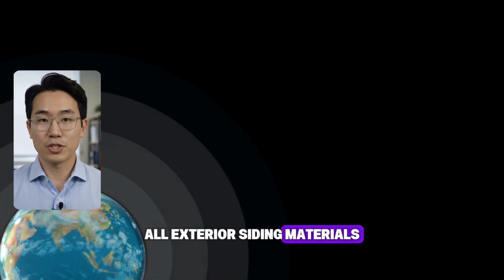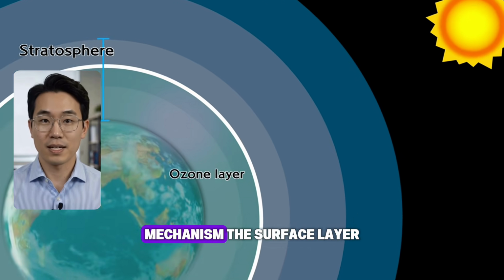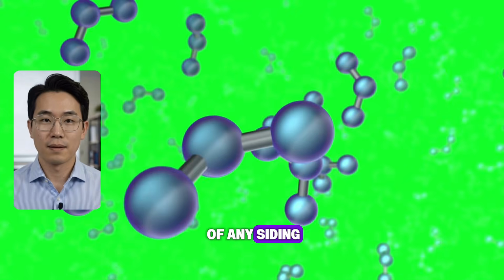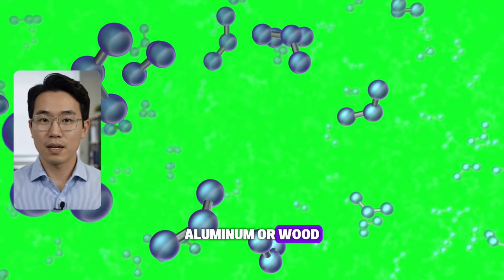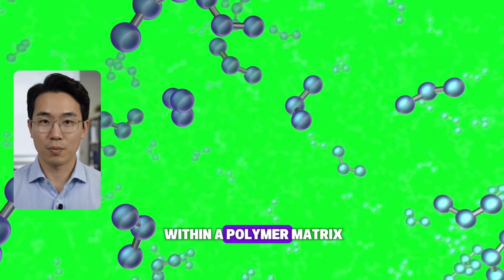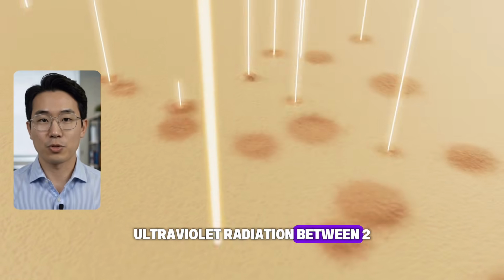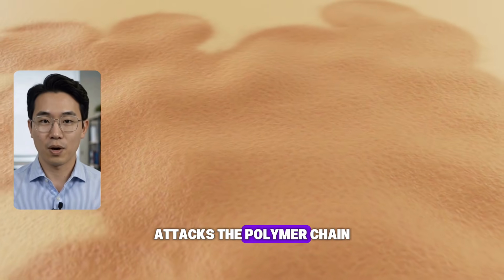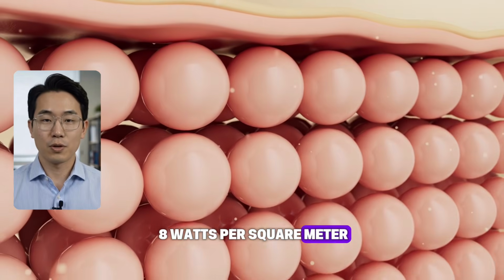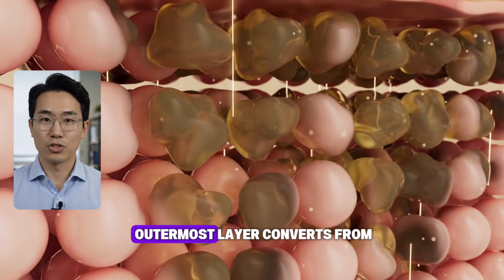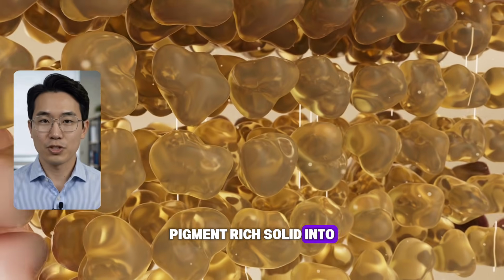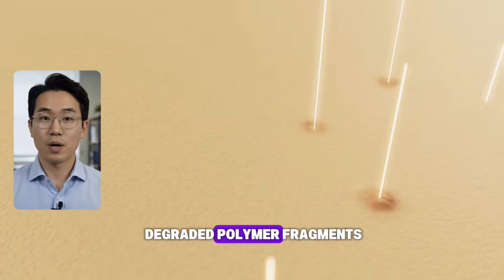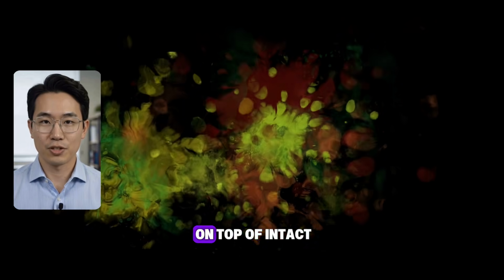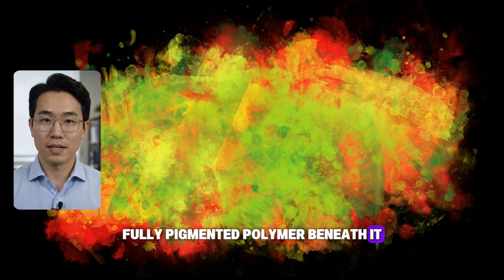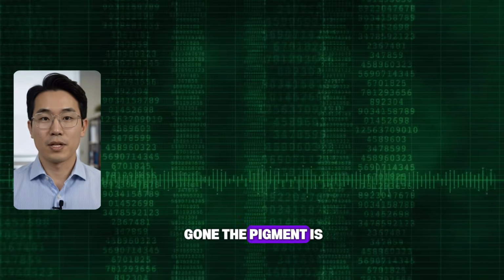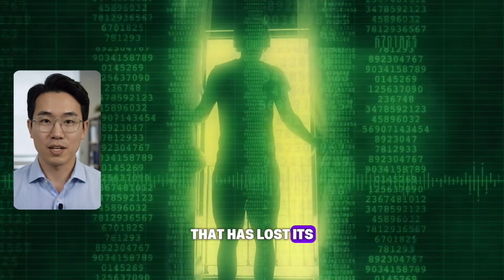All exterior siding materials degrade through the same fundamental UV mechanism. The surface layer of any siding, vinyl, fiber cement, aluminum, or wood, contains pigment molecules bound within a polymer matrix. Ultraviolet radiation between 290 and 400 nanometers attacks the polymer chain bonds at 4 to 8 watts per square meter in full sun, accumulating until the outermost layer converts from a dense pigment-rich solid into a loose, powdery, chalky layer of degraded polymer fragments. This chalky layer sits on top of intact, fully pigmented polymer beneath it. The color is not gone. The pigment is trapped inside a degraded matrix that has lost its optical density.